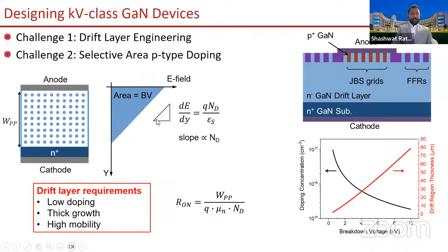So let's say you connect the anode on the top, cathode on the bottom. You connect the cathode to the N plus gallium nitride substrate. This is highly doped gallium nitride, which would have high conductivity, but you cannot use N plus gallium nitride to block voltage, right? If you apply an electric field to a metal, it cannot sustain anything. That's what happens to N plus gallium nitride. It's only used to make a bottom contact, but your workhorse remains this lightly doped gallium nitride layer.